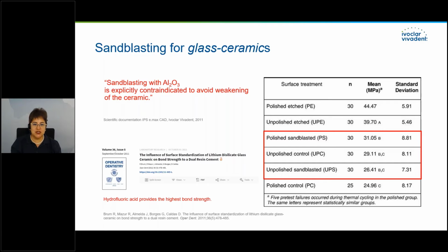Look at the results of this study. If you sandblast and polish, you will have 31 megapascal. So it's only 2 more megapascal than the control group where you do not do anything. And if you etch with hydrofluoric acid on a polished surface, like we recommend, you will have a significant growth of 15 megapascal on the bond strength. Therefore, sandblasting of ceramic has no advantages. Maybe it has big disadvantages in regard to bond strength. And the conclusion of this study is that hydrofluoric acid provides the highest bond strength.